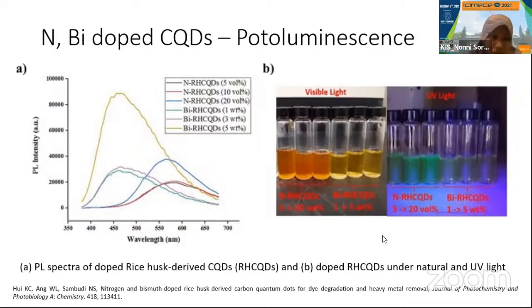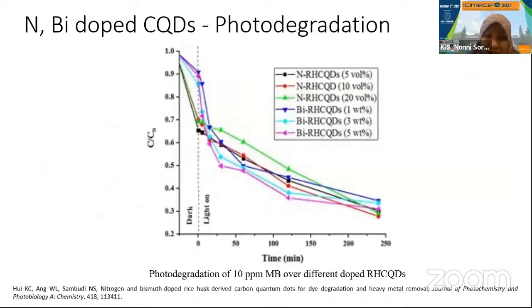So what we observe after the doping is the one that we dope with the bismuth has a blue shift. It goes to the UV light area, while the one that we dope with the nitrogen is going red shift. So it goes to the visible light area. So after we did the photodegradation test, again by using the same 10 ppm methylene blue, it shows that the nitrogen-doped carbon quantum dots has the best performance.